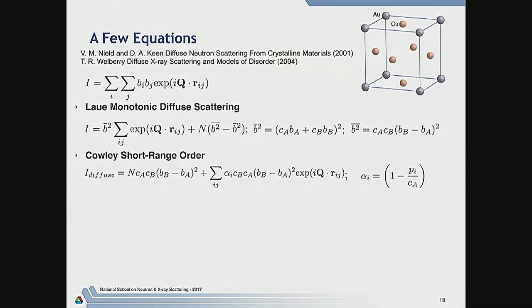Now, instead of having something completely random, we have these Cowley short range order parameters, now often called Warren-Cowley short range order parameters, which represent deviations from the average. So what these parameters show is that if you have an atom A, then if you go to the vector Rij, the alpha I will have this value, where this is the probability that if you have a site to atom B, then the site that's Rij apart is an atom A. And you can see that if the probability is just the average, in other words, CA, then this will go to zero and this will drop out and you'll end up with just the monotonic scattering.